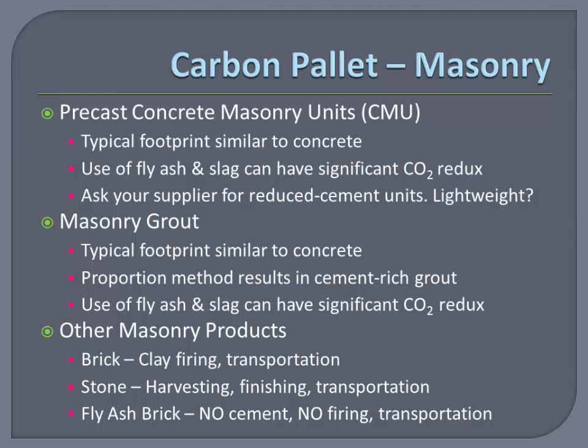For masonry grout, one of the most common ways to specify masonry grout is the proportion method. It's easy, it doesn't require any field testing, but take a look at those mix designs for the proportion method grout, and you'll find that it's 6.5 or 7.5 bags of cement. Bags, I'm showing my age. You know, 600 or 700 pounds of cement per yard of grout, which only needs to be 2,500 psi. So specify the strength method, require the prism tests, and you can probably cut the amount of cement down by something like half. You want to cut your carbon footprint in half? Just do it. Is this any additional cost? No. The grout's a little cheaper, the testing is a little bit more, but essentially it's a no-cost benefit to reducing carbon.